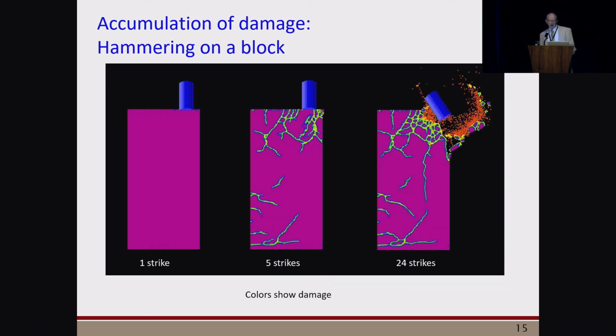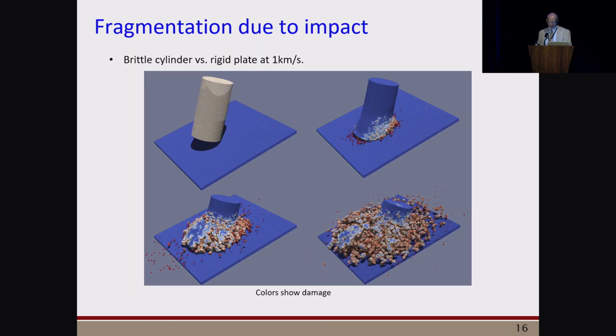One feature that you get for free with peridynamic modeling of damage is you accumulate these broken bonds over time. So this is a simulation in which we hit the edge of this brittle plate with a hammer many times. And each time you hit it, the damage that was already there grows farther, plus you introduce new damage. And eventually the hammer breaks through, and you can see some of this so-called peridynamic dust that is created in this meshless discretization.